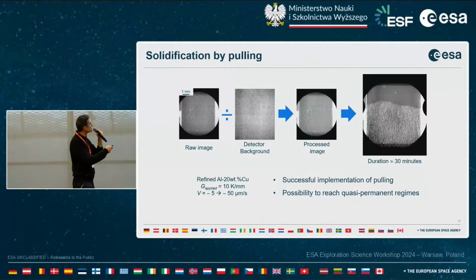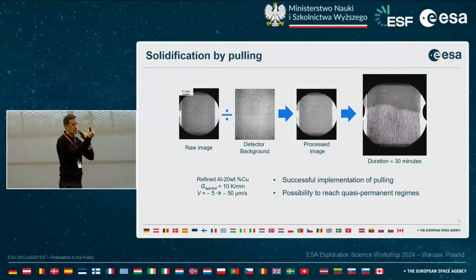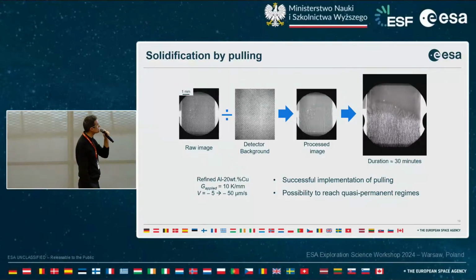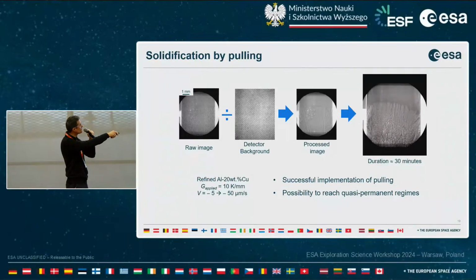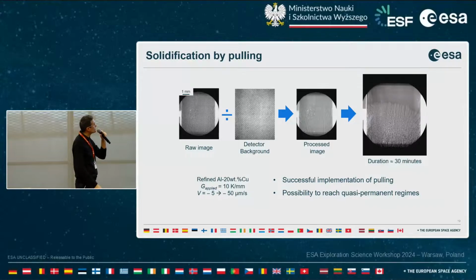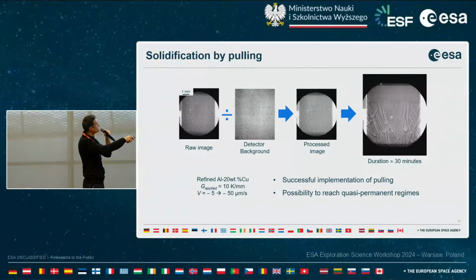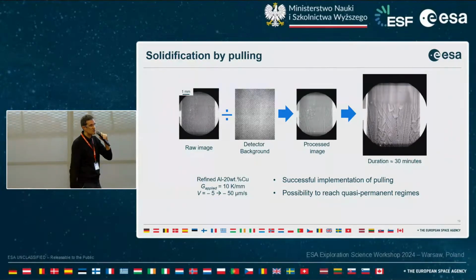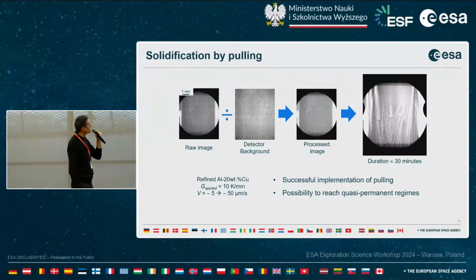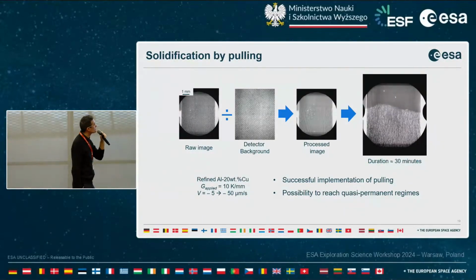And here is an example, this time, of a pulling experiment. The sample is partially melted, so we have liquid and solid, and then the sample will be moved toward the cold zone. We will observe the solidification of dendrites. We only see the top of the solidification front, but clearly here it was at low velocity, and we increased the velocity to observe the change in the microstructure. It was working quite well.